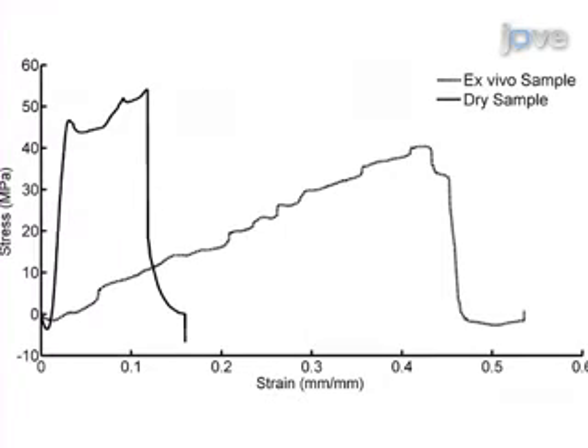These are representative plots showing the stress-strain curves for a dry sample and an ex vivo sample that have been implanted in a rat cortex for 30 minutes. The Young's modulus, which corresponds to the slope of the stress-strain plot in the linear elastic region, is clearly much greater for the dry sample. Both samples were strained to break.